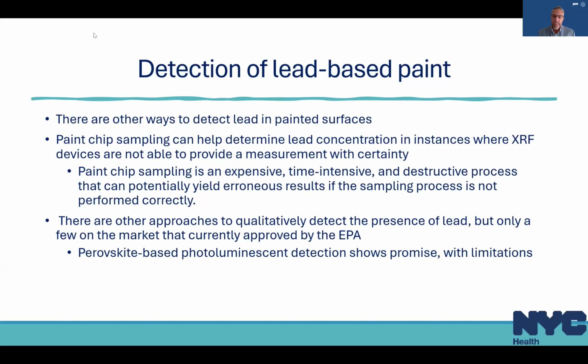There is a promising, relatively new approach, perovskite-based photoluminescent detection. It's basically you take a solution, you score a surface, scratch a surface, you spray it, and then you shine a black light on that surface, and it illuminates if there's lead there, and the magnitude of the illumination can be correlated with the concentration of lead. Again, it doesn't tell you the number, but it just gives you a sense on whether or not a product may have lead in it, and maybe if further investigation is warranted.